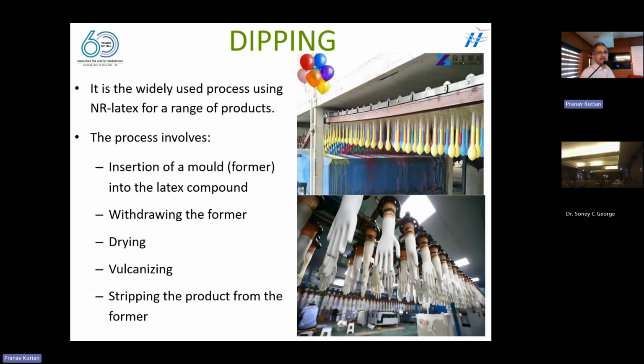These are the examples. As I told, dipping. This is the most widely used process for products made of latex. This is the balloon and the gloves, where the former, which is a porcelain former or a wood former or a glass former, is inserted into the polymer, the concentrated latex, which is mixed with ingredients like sulfur, antioxidants, acids, accelerators, etc. And of course, color. These are also given, and this is then withdrawn from the latex and kept for drying in the oven at a specific temperature, maybe 70 or 80 or 100 degrees Celsius, for a specific period of time, which will give a final product. And this can be taken out from the mold by undoing. The stripping is happening.